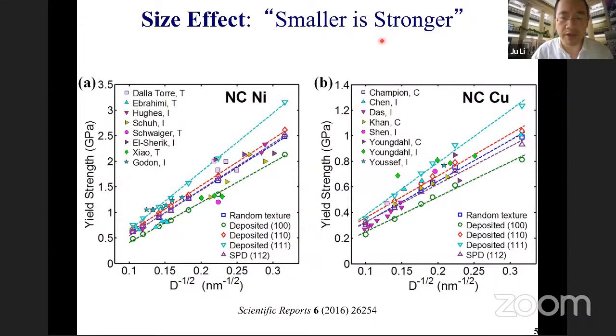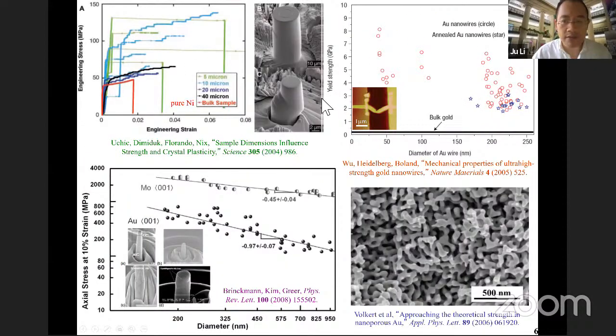This is fundamentally because when you reduce the characteristic grain size or sample size, the strength goes from defect propagation controlled to defect nucleation controlled, because these boundaries destabilize defect sources like the Frank-Read source and fundamentally change the defect population dynamics. This has been seen, for example, in nanopillars: as we reduce the diameter of nanopillars, the strength goes up. And in the limit, you can get nanowire strengths or nanoporous material strengths. They're all very, very high.